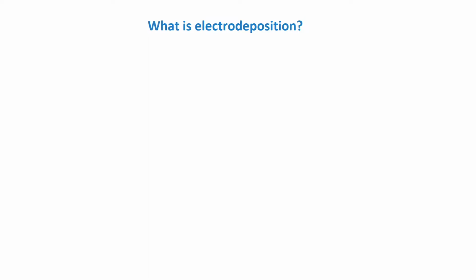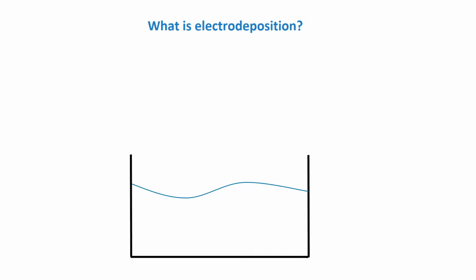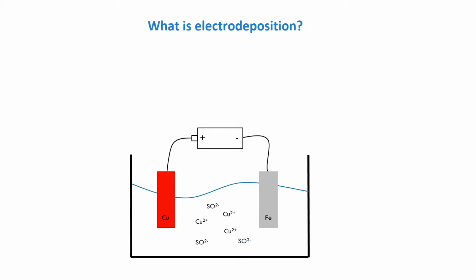Let's start by explaining what electrodeposition is. As we can see from this schematic representation, the electrodeposition process involves the use of an electrolyte to transfer the species of interest, two electrodes, and an external power supply to drive the deposition process. In this example, we are applying a certain current input to accelerate the dissolution of copper anodes and to drive the dissolved copper ions to be deposited at the cathode surface. So, after a certain time, our cathode surface will be covered with a layer of copper.